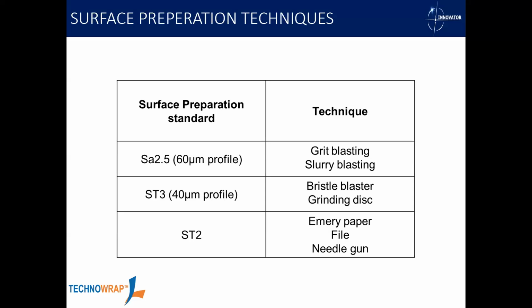In some circumstances, we can apply on hand prepped profiles, but if you've ever tried using emery paper and files and needle guns, it takes a very long time to even remove a layer of paint. So it can be very difficult to get a very rough profile and a very clean pipe as well. But it may be suitable for low pressure drain lines, but anything more than a bar or two, it wouldn't be suitable whatsoever. So generally always aim for the best, which is the grit or sandblasting to SA 2.5 and 60 microns. Next slide, please.